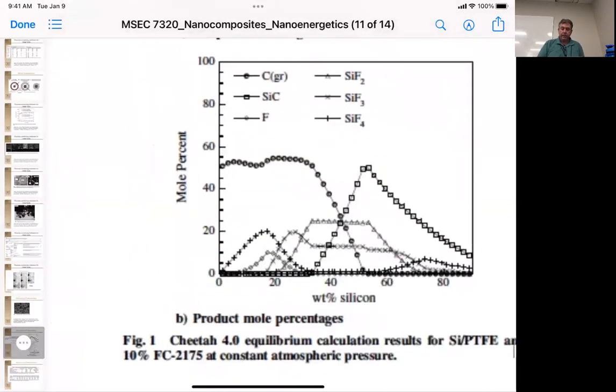Okay. And then what they looked at was the products. And this is a really interesting program. It's a thermodynamic calculation program used by people who do explosives and energetics. It's called Cheetah. And they can predict what products come off at different parts. So if you look at this one right here, this is carbon. As we start with 0 silicon and we move to more and more silicon, we actually get less carbon out of the system. In fact, we see a rise of silicon carbide. So it's actually making silicon carbide, which is also another high melting material. So that's not actually highly desirable.